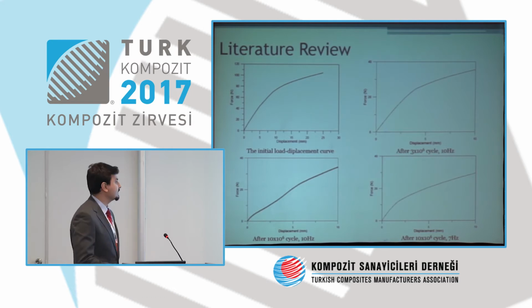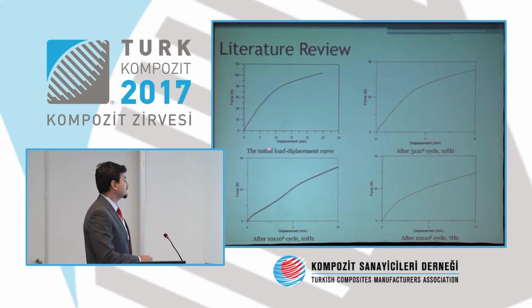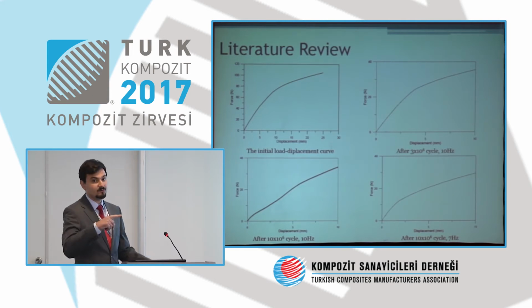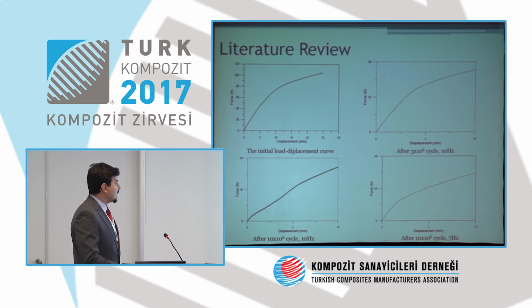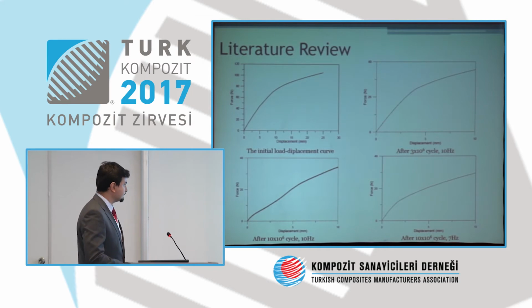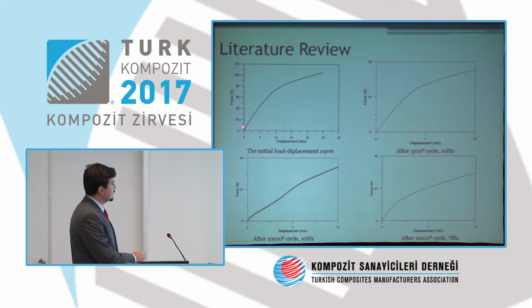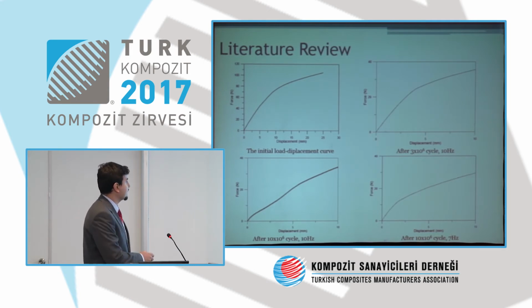they published only their stiffness loss, actually. This is the initial load displacement curve before fatigue tests. These are after the fatigue tests. You can see the stiffness loss here. The stiffness is the tangent of this linear area.